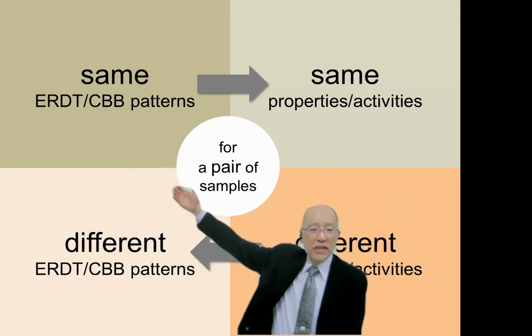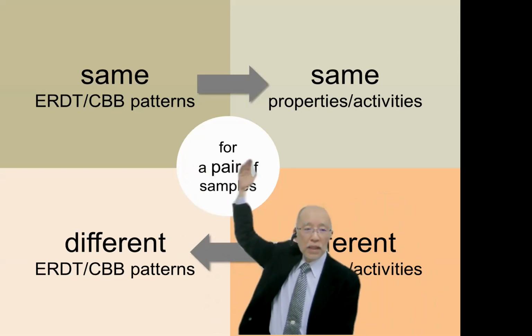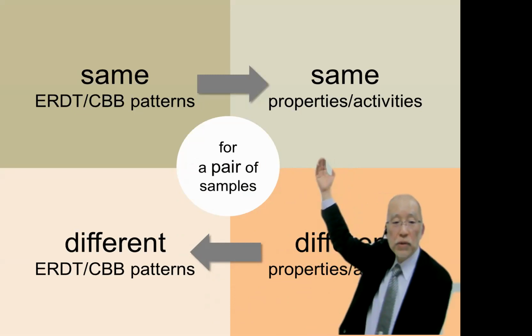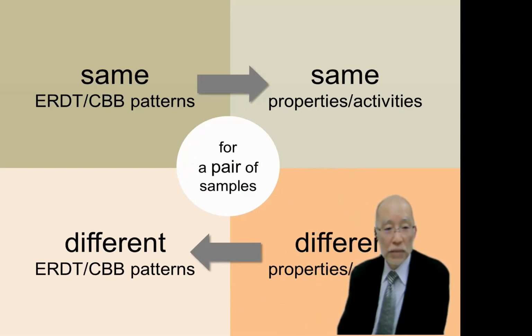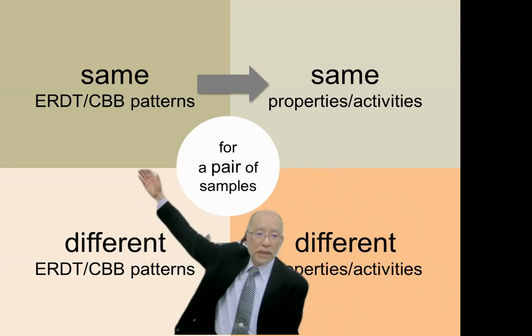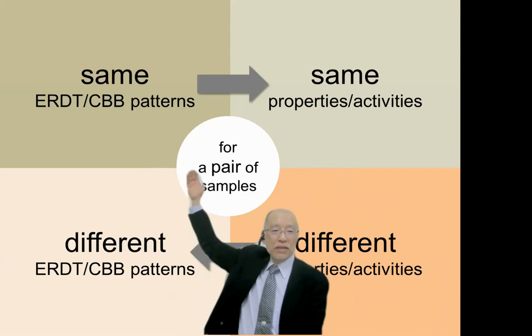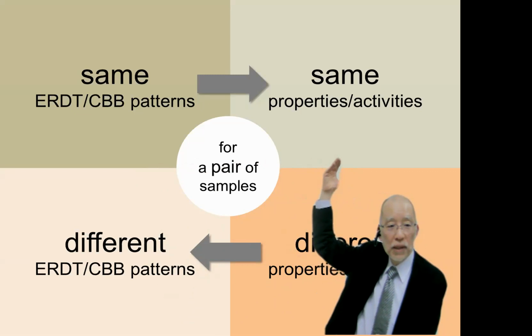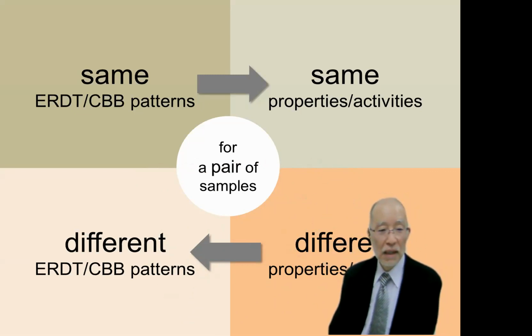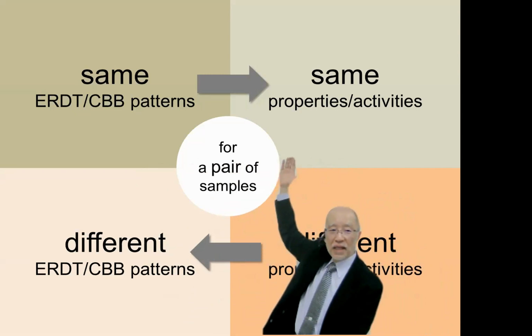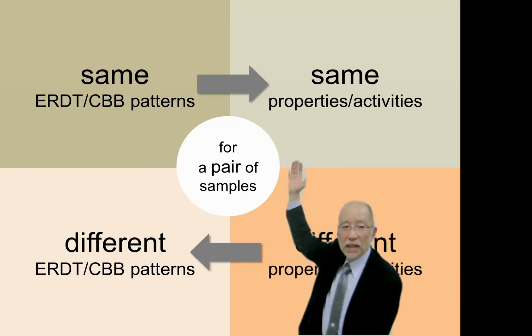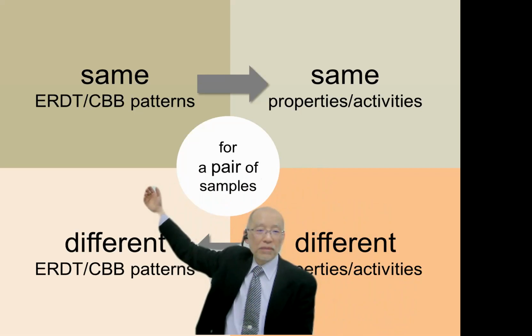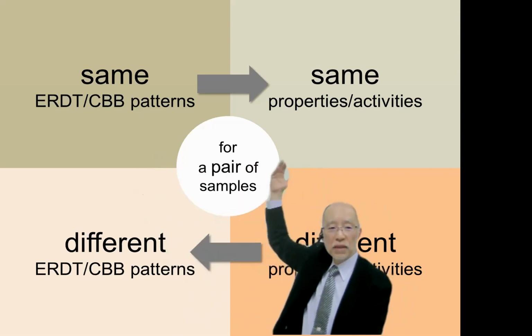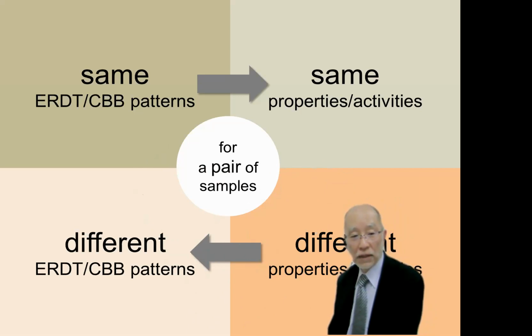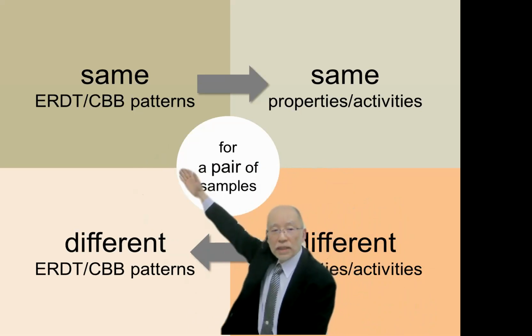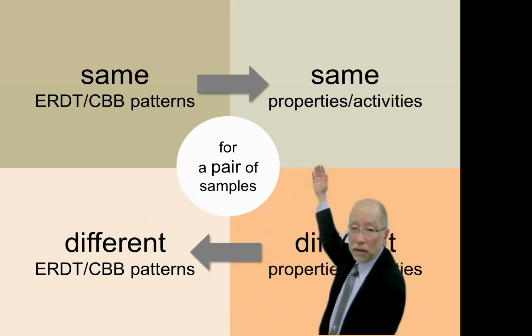But if the same patterns of polishing material are obtained, the polishing ability is almost the same, even for those physical properties. Because the ERDT pattern is just a fingerprint, and if they are the same, they must be the same material. So they must show the same property, activity, and performance. But if the same property or activities are obtained, the ERDT/CBB pattern cannot always be the same. A different pattern sample gives the same activity or performance accidentally. Only this way: same pattern, same activity, same property.